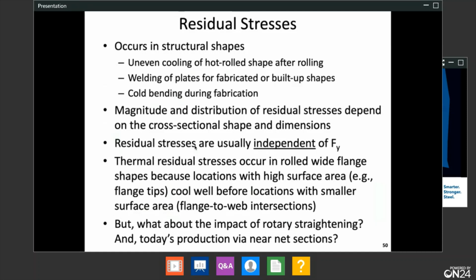A couple important things to note: the residual stresses are almost always independent of the yield strength of the material. We tend to say, oh, they're about 0.3 Fy or 0.5 Fy, and I'll show those slides in a minute. But once we go to the high-strength steels, that is not the case. They're a pretty fixed number. And when we rotary straighten them, or even just put more emphasis on using near net sections before the rolling even starts, we tend to have much smaller residual stresses, if any.